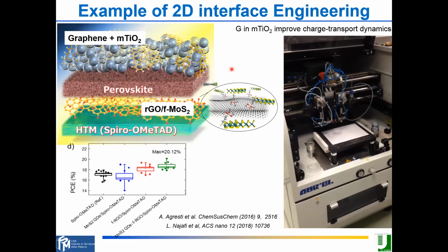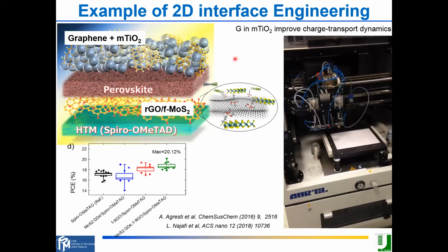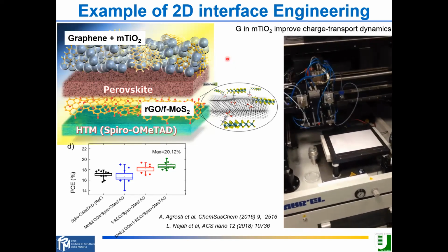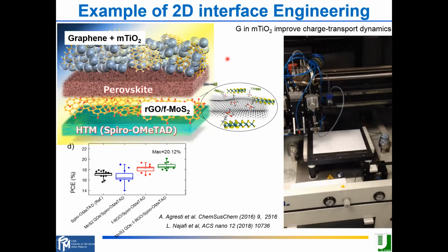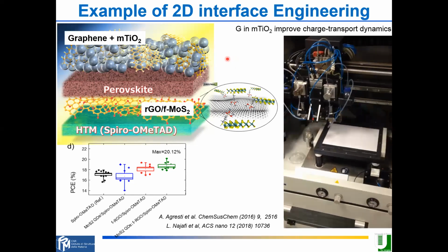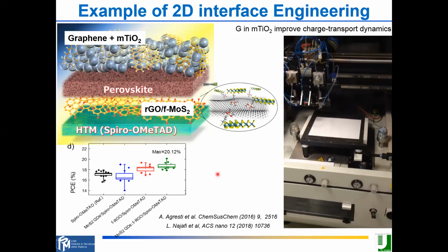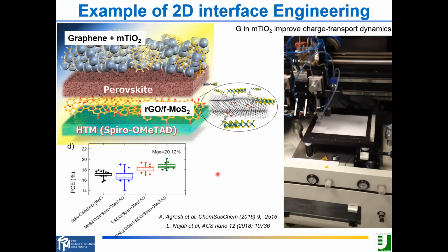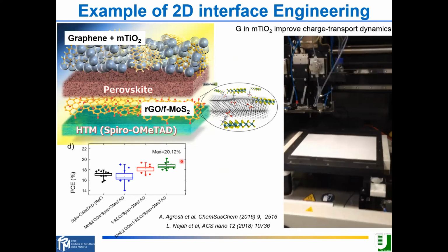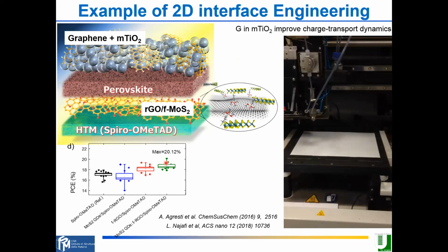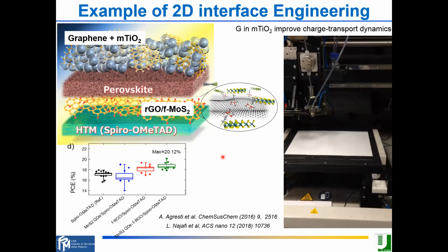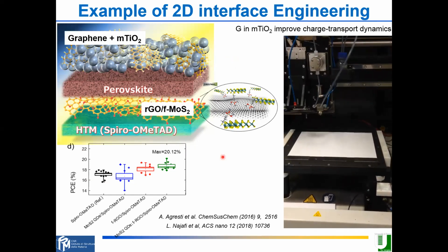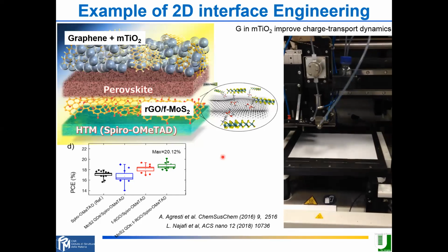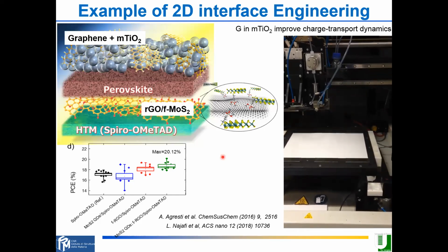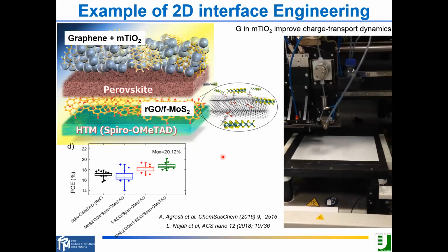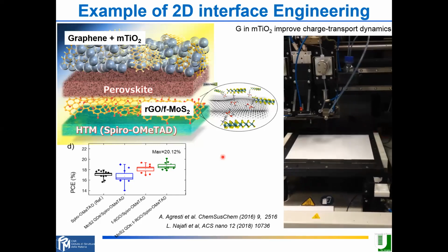And the deposition was very simple. We were using a spray coating technique for the 2D material, so it's still a solution process. And you see with the mapping, very simple, the most simple perovskite you can imagine. We were able to push the efficiency of the solar cell even beyond 20% by tuning these interfaces. This is not limited to the efficiency. This also has a strong impact.